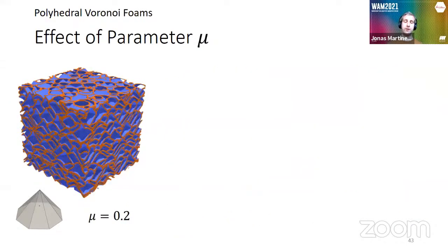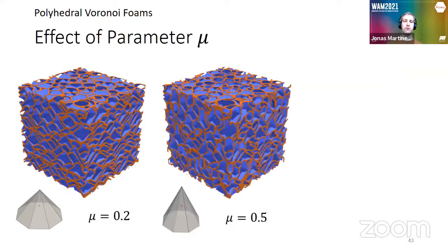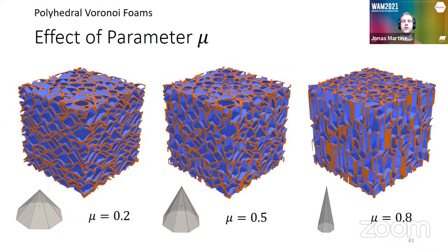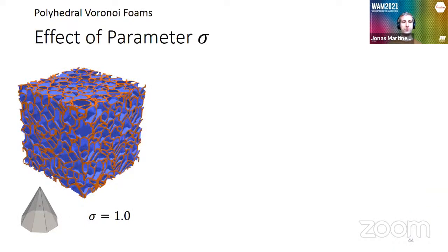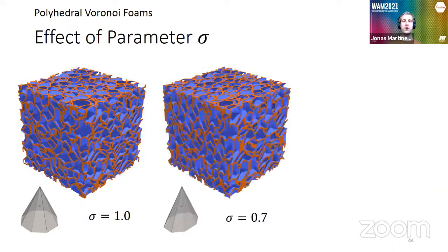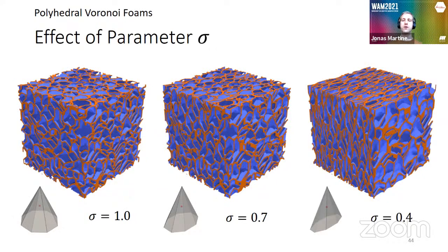Then you have the parameter mu. This is a very interesting one. This one, I'm going to show it visually, intuitively. What it does, it controls the amount of vertical walls versus non-vertical walls. All right, so as you can see onto the left, you have almost no vertical walls, but onto the right, you have this kind of more elongated vertical walls. You also have the parameter sigma. This is the stretching. So you see, we start stretching this distance, and this stretching of the distance also incurs a stretching of your metamaterial. So as you can foresee, mechanically, this means that we will have more stiffness in the direction where we stretch, and in the perpendicular one, it's going to be less stiff.